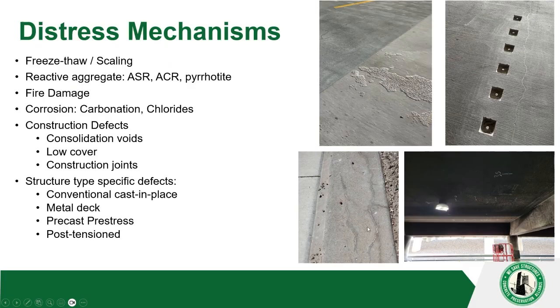This photo right here is ASR, alkali silica reaction. You can have multiple different types of reactive aggregate. The alkali silica reaction is the most common. You have alkali carbonate reaction, which occurs with microcrystalline quartz in limestone. And then you have pyrrhotite. Pyrrhotite is an iron sulfide mineral that is mostly a problem in the Northeast, like Northeast Canada and Northeast US. And then you have fire.